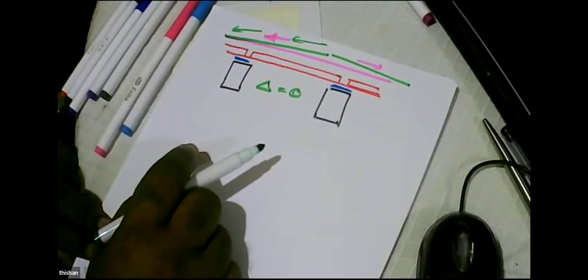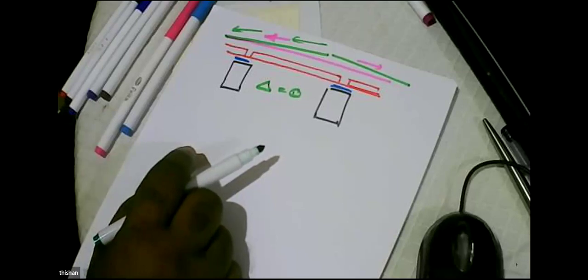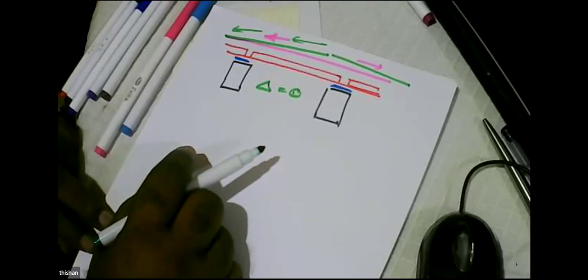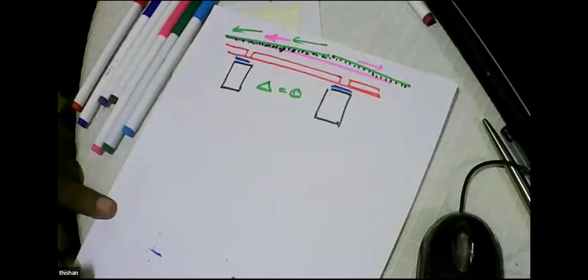But the beauty of this system is deflection is zero. So there's no sagging in the slab, because most of the time you will find due to creep and shrinkage, slabs sag. And this sag causes water to stagnate. And when the water stagnates, then all the problems will come, and waterproofing problems will be there due to that reason. So what we can do is embed chips so that chips will not wear out, though the cement can be washed away, but not the chips. So we create chips here.